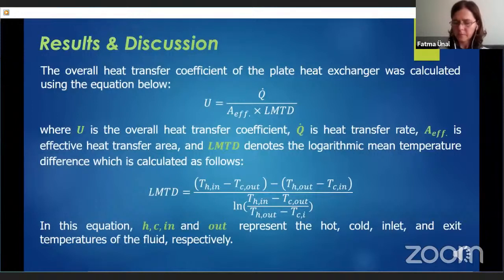As to theoretical analysis, the overall heat transfer coefficient of the plate heat exchanger was calculated using this equation. In this equation, U is the overall heat transfer coefficient, Q dot is heat transfer rate, A eff is the effective heat transfer area, and finally LMTD denotes the logarithmic mean temperature difference, which is also calculated using this equation. In this equation, H, C, in and out represent the hot, cold, inlet and exit temperatures of the fluid respectively.